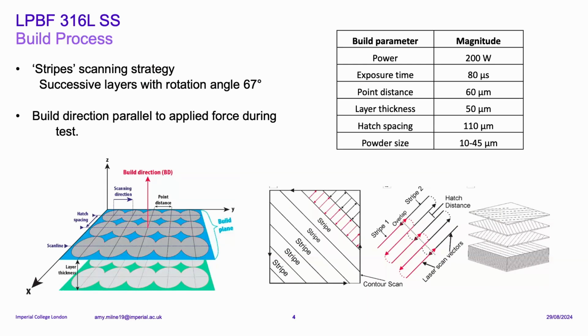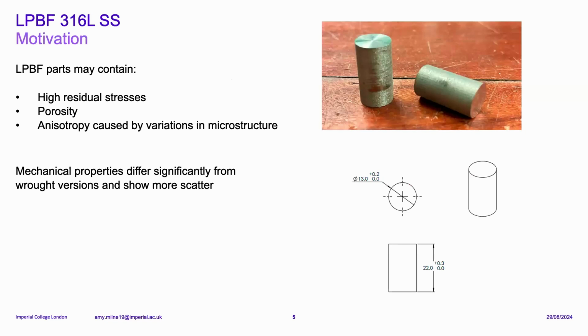So for my samples, we used a stripe scanning strategy with a rotation angle of 67. You can see the rest of the build parameters on the side of the screen. The build direction was also parallel to the applied force during a test, and you can see what I mean by that from the picture up there. You can see the stripes going upwards and the force is being applied downwards in the compression test. So it's the same build direction.